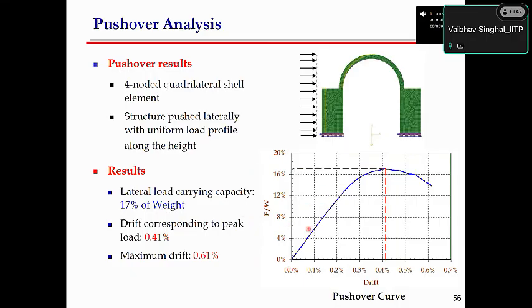One can see that at a drift of about 0.4%, this dome or this arch has reached a peak capacity, which is about 17% of its weight. If you put the seismic capacity in terms of weight, it gives a better understanding about its capacity. So it was found to be approximately 17%.